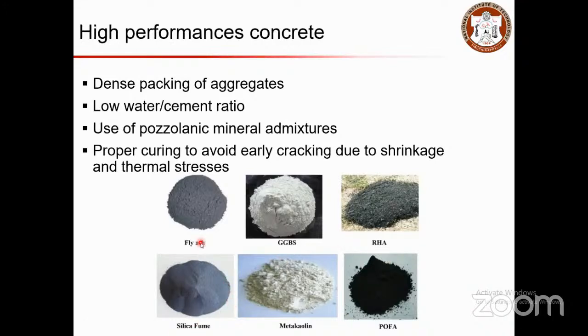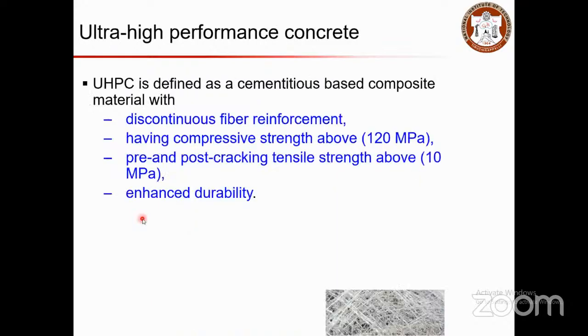The advantage of using such materials is that some of them are finer than your cement particles, so they will fill in the pores and help you to get a densely packed structure. Some materials will react with the calcium hydroxide in your cement and produce additional CSH, which will also help you to get more pore refinement and a denser matrix. This requires proper curing to avoid early cracking due to shrinkage and thermal stresses, because when you use such materials they need to be taken care of properly. Then you have ultra high performance concrete.